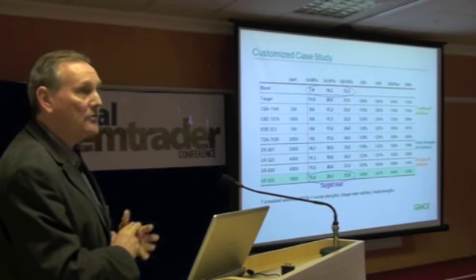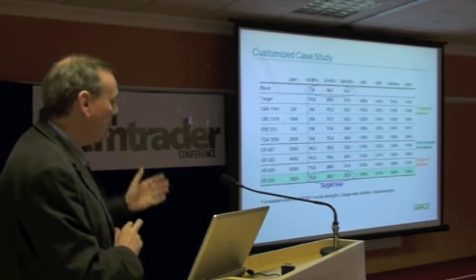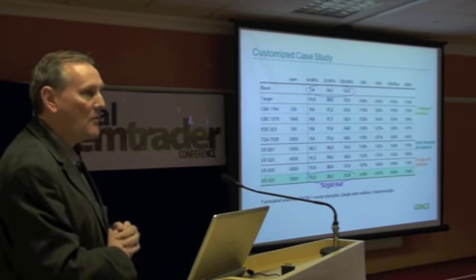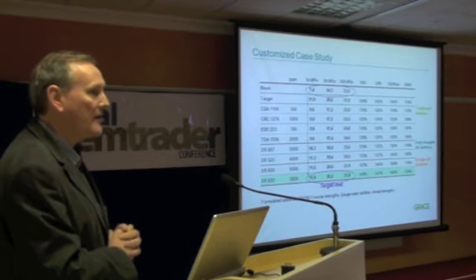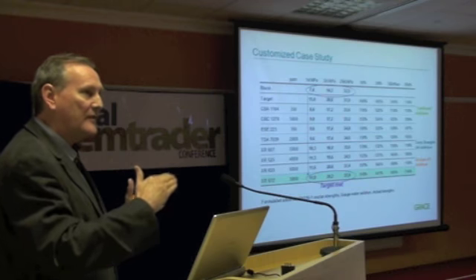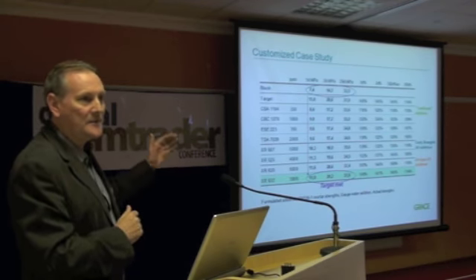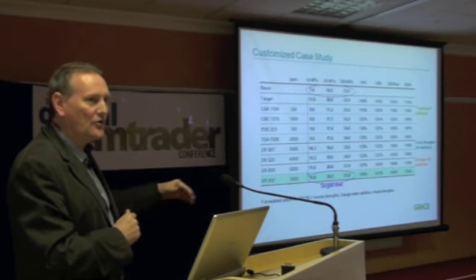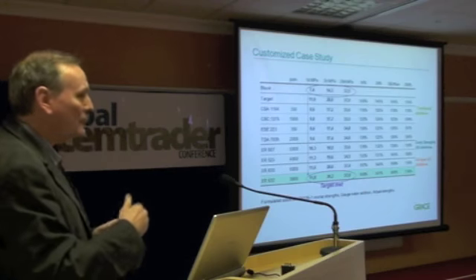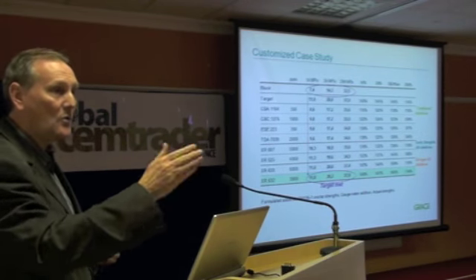That's 300 to 400 parts per million, up to about 2,000. This is 3,000, although now it's been in use for 2 years, and I think they're using it at about 1.5, so 1,500 grams per tonne. It's brought the costs down, some of the benefits down, but it's all about that balance. It's easy to make the prediction of dose and cost, because we give a price, and the more they use, the more it costs per tonne of cement. But it's not so easy to assess the benefits, because it's not always a linear response.